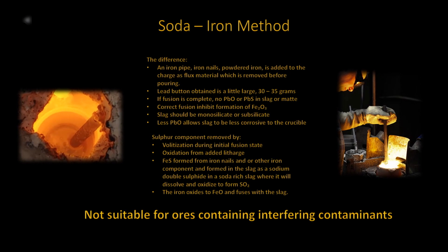There is a difference when comparing soda iron fusion with the other types. The iron component as a flux is reducing. However, it is not controlled or calculated. The lead buttons that are usually produced are larger, about 30 to 35 grams in size. Enough litharge is added to combine with the lead in the ore, if any. That is, if all the lead is reduced, the buttons will be 30 to 35 grams.